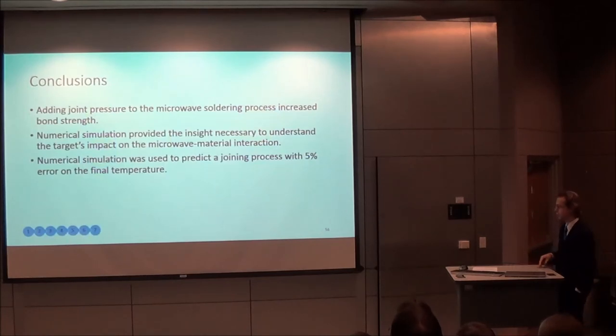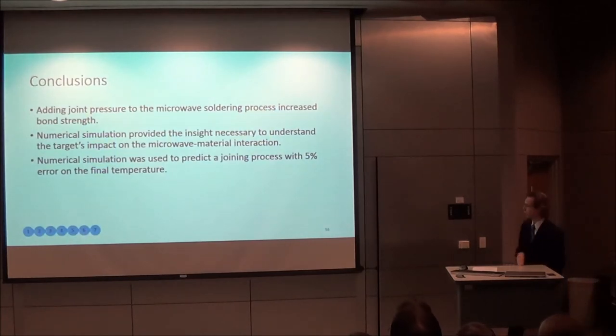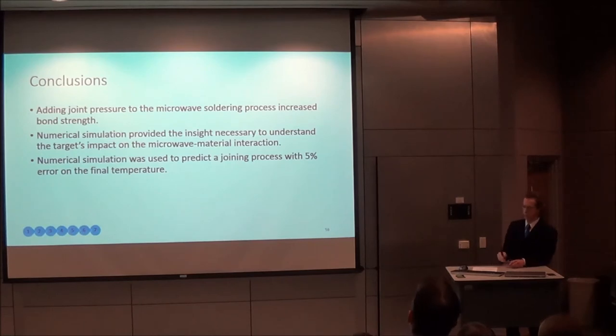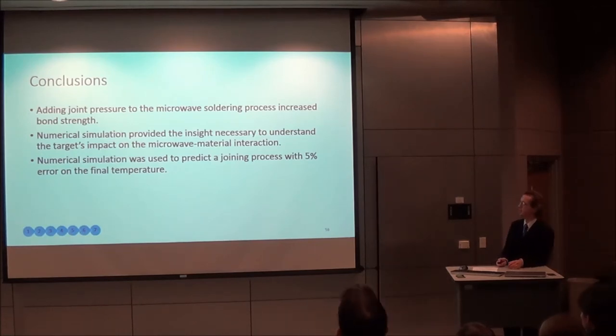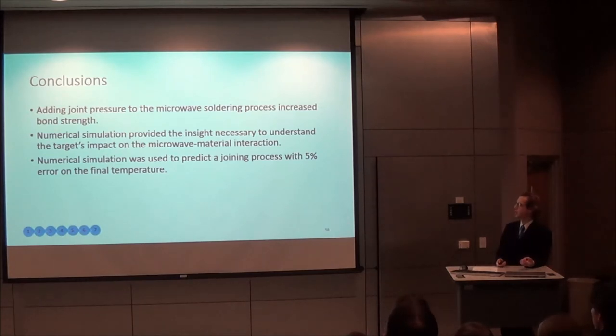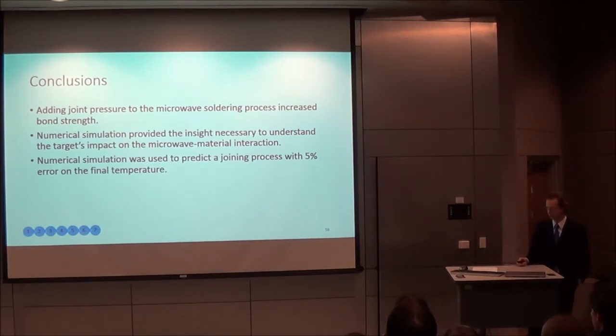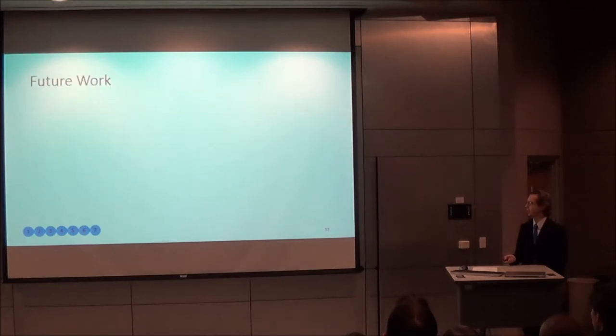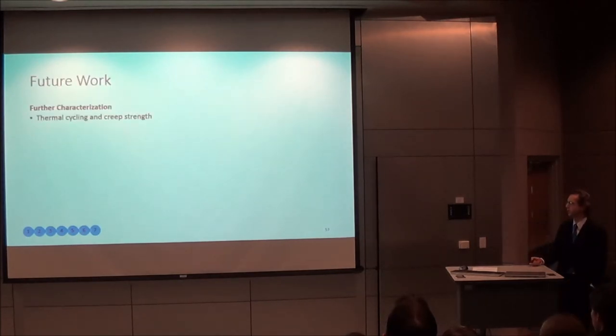So the conclusions of this work are that by adding joint pressure to the microwave soldering process, the bond strength of the joint was increased significantly. Previously, this kind of joint could be pushed apart in your fingers. Numerical simulation provided the insight necessary to understand fundamentally the microwave material interaction in a better manner and how the target impacts that. The numerical simulation was also able to predict the final temperature of the experiment within 5% error. Some future work that should be done: further characterization of this solder joint.